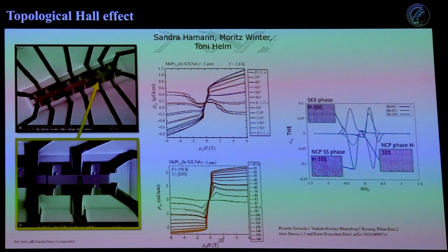And then I said, yeah, okay, now we have to go below this high temperature. This is actually still a little bit below the spin orientation. So you still have some interesting things here. But then we go very much below, about, I think, 1.8 Kelvin. And you still see when you have your magnetic field perpendicular to, or parallel to the c, you have some hysteresis here, which gives you topological Hall effect.